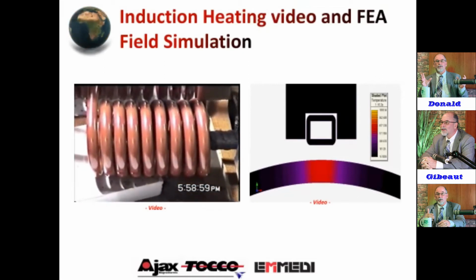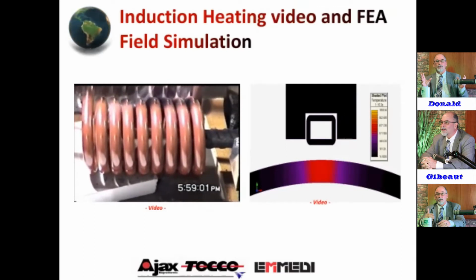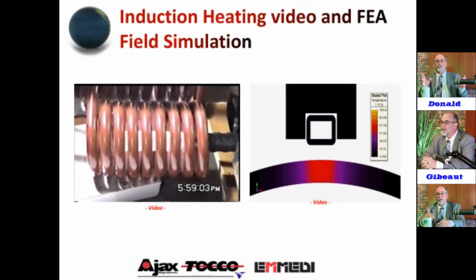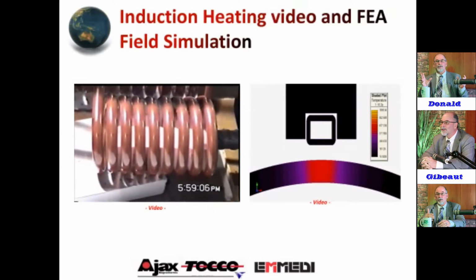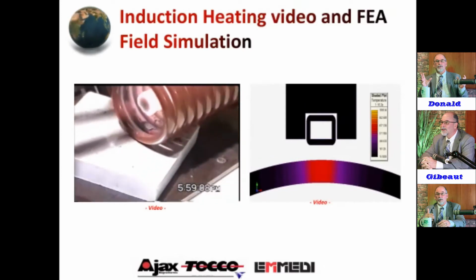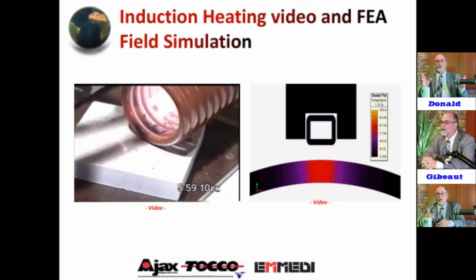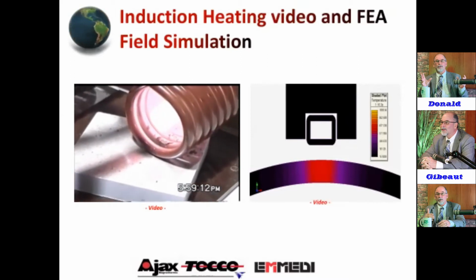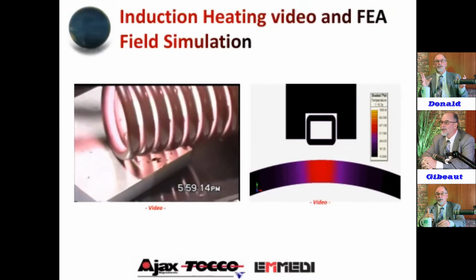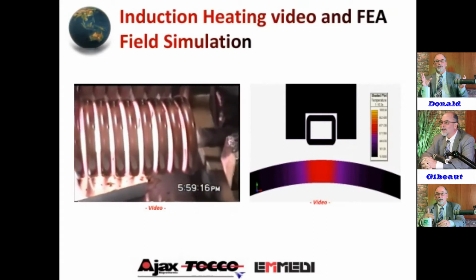Now watch the side heating through the copper coil here that is insulated. You've got cold wall conduction, so we overlap the coil a little bit on this side. The other end, you have radiant losses out the end, so you've got to have an overlap of the copper coil to compensate for that. But there's rules of thumb, and it's very precision set.